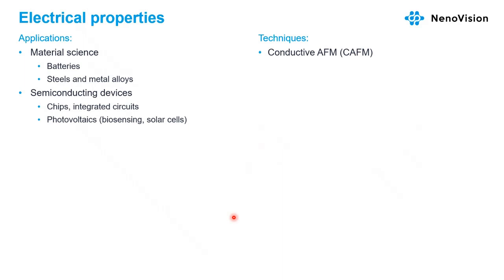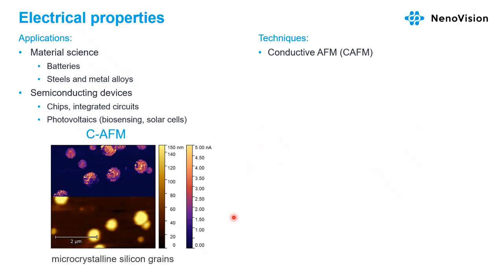The conductivity map can be obtained using conductive atomic force microscopy mode. We see half of the image as the topography, the other half is conductivity. And so we see the microcrystalline silicon grain sample, and there are visible grains which are conductive compared to the rest of the sample.